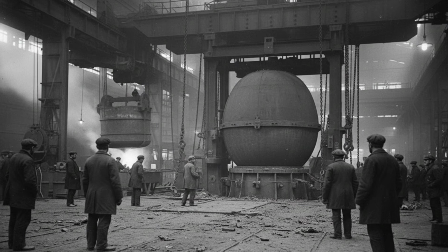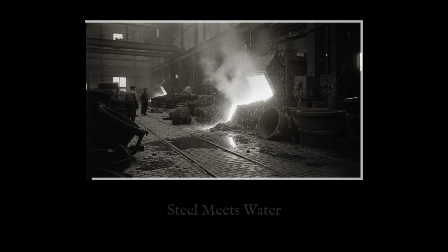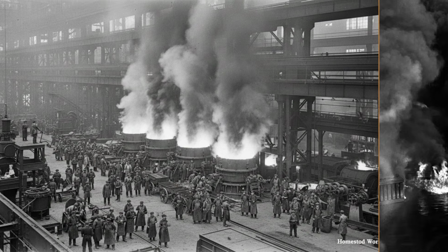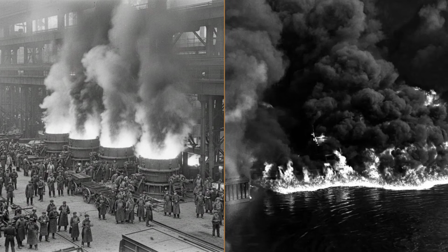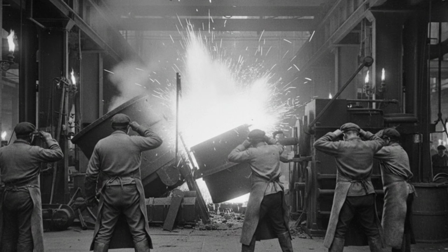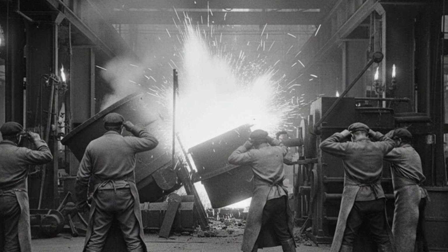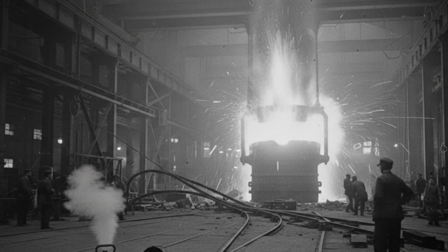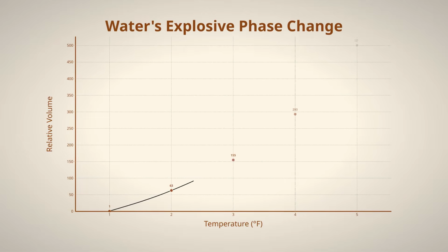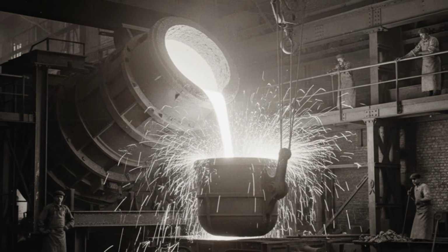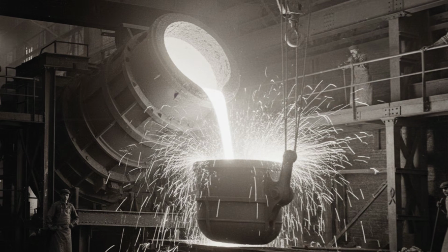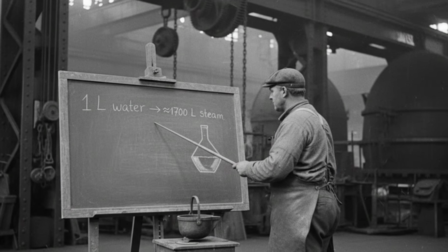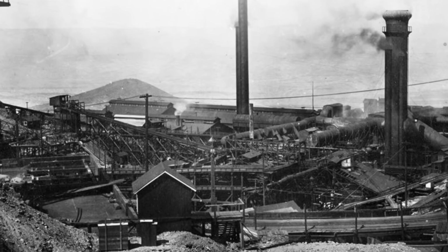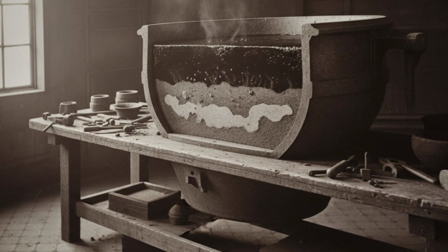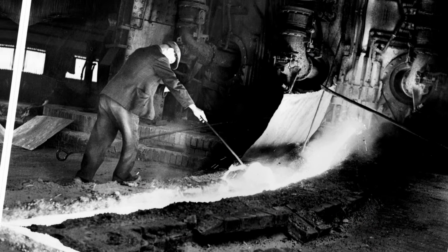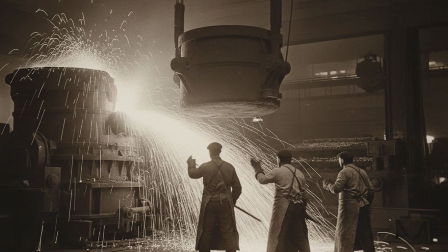But the ladle drop was not even the worst scenario. The worst scenario was liquid steel contacting water. Steel at 2,900 degrees and water, even a small amount of water, produce a steam explosion so violent and so fast that the men who witnessed them and survived described it as an artillery shell going off inside the building. The physics are simple. Water vaporizes into steam at 212 degrees Fahrenheit. At 2,900 degrees, the conversion is essentially instantaneous. Water expands by roughly 1,700 times its volume when it turns to steam. If that expansion happens inside or immediately beneath a mass of molten steel, the steam has nowhere to go but up and out, carrying the steel with it as a projectile spray.